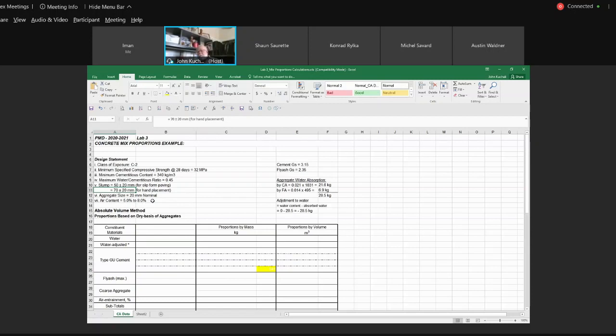And our air content, we've known that with C2, freezing and thawing and using the icing chemicals, we have to have an air content between 5 to 8%. Now we're going to design on the higher end of this range, and I'll tell you why a little later, but most people will say, well, I'm going to design right down the middle, okay, 6.5. You can, nothing wrong with that. But my past experience has shown that every time concrete comes to the job site, if you're batching at the plant for 6.5, chances are you're going to be close to the bottom end on the job site. If I design my mix on the high end and I lose 0.5% to 1% on the job site, I'm right down the middle where I should be.